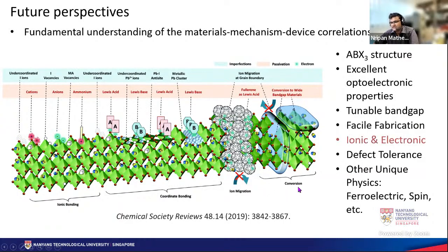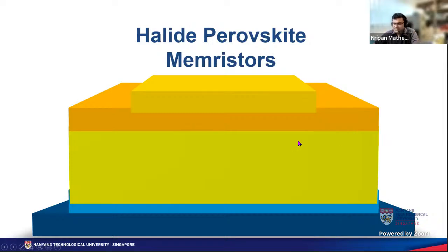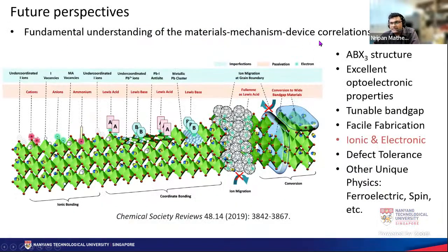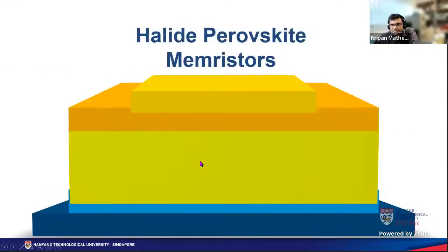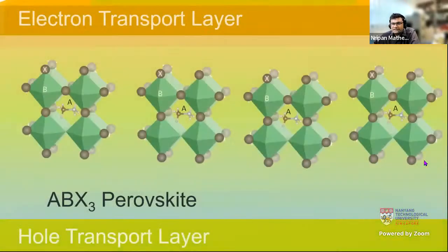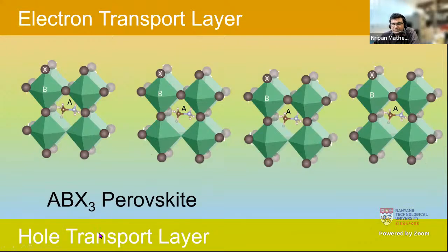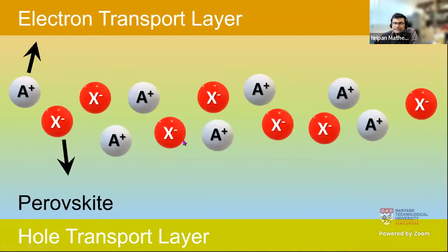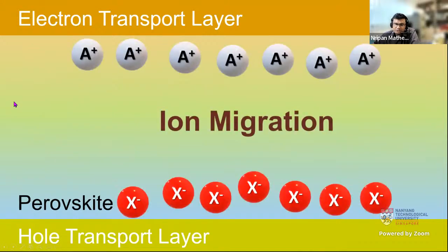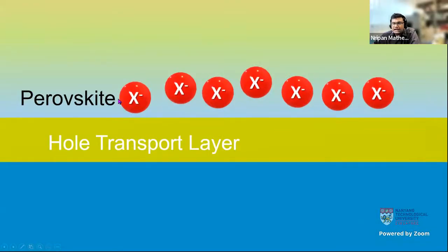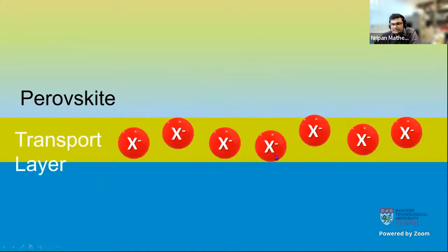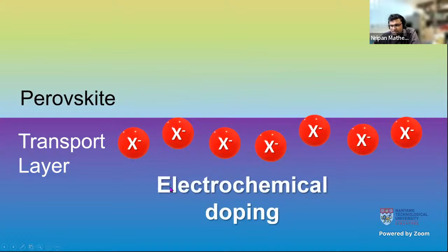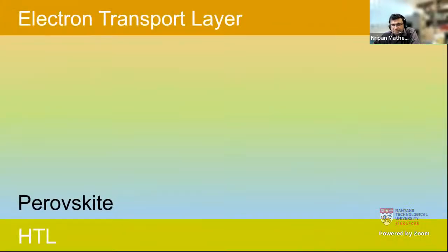But this also means that we have a lot of challenges, and we need to understand a lot of the materials mechanism. Device correlation is still pretty new. If you zoom into a halide perovskite memristor, and this is the architecture that I talked about, normally we always have a hole transporting layer and electron transporting layer sandwiching the perovskite layer. On the application of a voltage, the halogens, the X minus halogens or the A side cation can start to diffuse. So you could have ion migration within the perovskites. Halogens can diffuse into the interfacial layer and can lead to electrochemical doping. That is a mechanism that we can utilize.